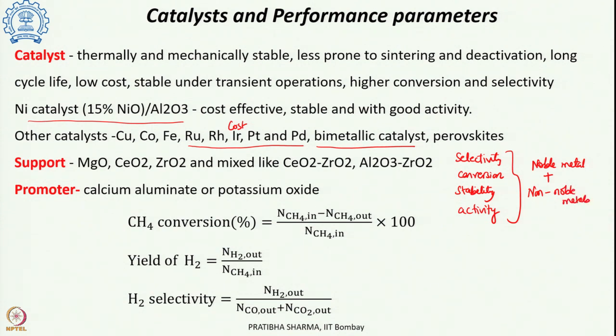Other than the transition metal and noble metal catalysts, perovskites are also being used as catalysts. There are various supports that can be used like magnesium oxide, cerium oxide, zirconium oxide, and these can be mixed together. So, when alumina and zirconia are used, they have better stability as well as better conversion. Zirconia provides good conversion, and it provides a little basicity of the support also, so it reduces coke formation. Ceria provides a higher thermal stability.